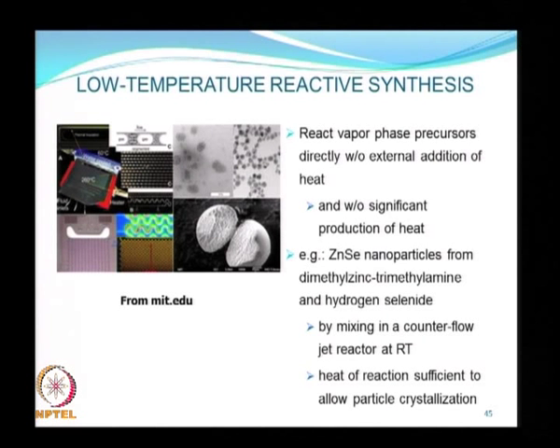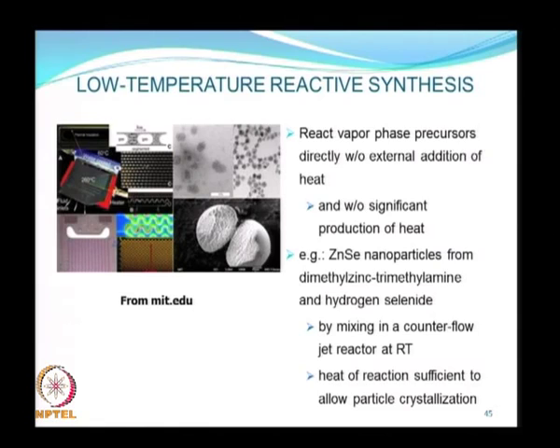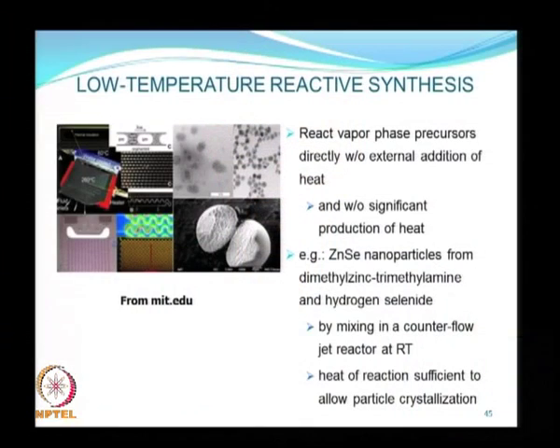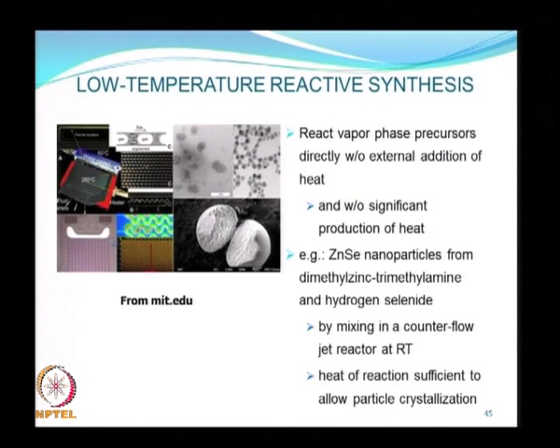All that is required is intimate mixing using a counter-flow jet reactor kept at room temperature. The heat of reaction itself is sufficient to allow particles to crystallize. It is a very energy-efficient process because it can be run at room temperature without external addition of heat, and the lack of heat generation also means it can be done in simple equipment designs without concern for heat dissipation.